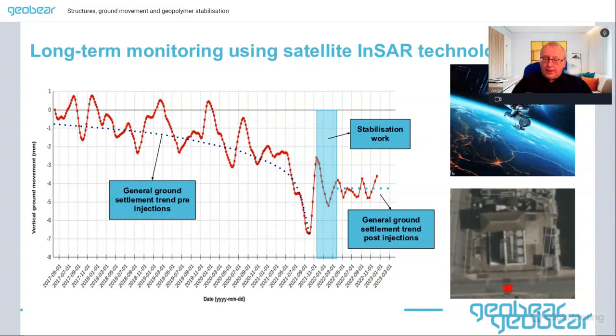And further to that, we then went and had a look at some satellite data to see how things improved. This was using some satellite data that was purchased for this particular section of road. And you can see over time, prior to the treatment, the levels on the road were continuing to drop quite significantly over a period of weeks and months. And after the stabilization work had been done, we had essentially arrested the continuing settlement of the road. So that confirms, from the density improvement and also satellite monitoring of the road level, that it had been stabilized, all done in a non-disruptive manner.